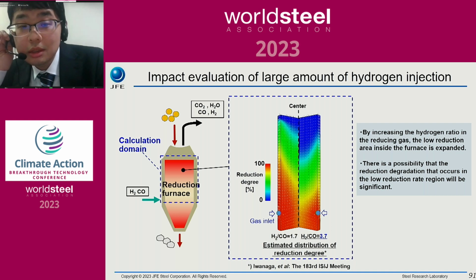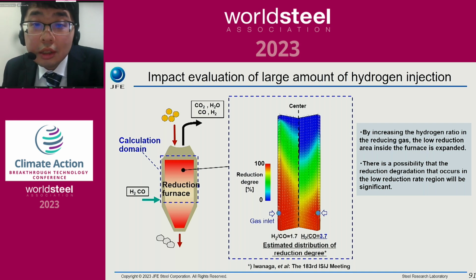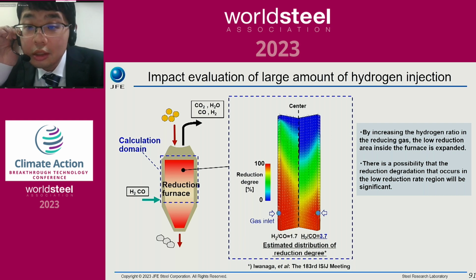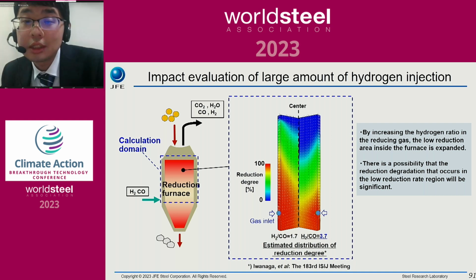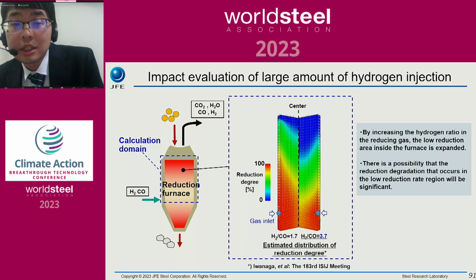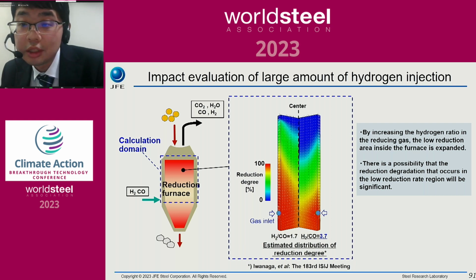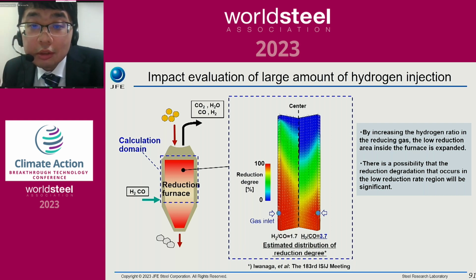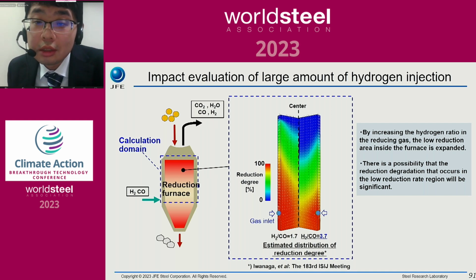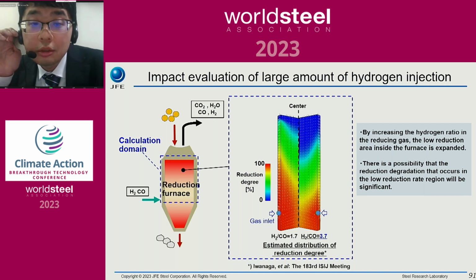And in this example, it is shown that the reduction in the reactor is delayed by increasing the hydrogen ratio, and the reduction degree in the center is lower, and this tendency becomes more significant when the hydrogen content in the reducing gas increases. And by increasing the hydrogen ratio in the reducing gas, the low reduction area is expanded at the upper part of the furnace.